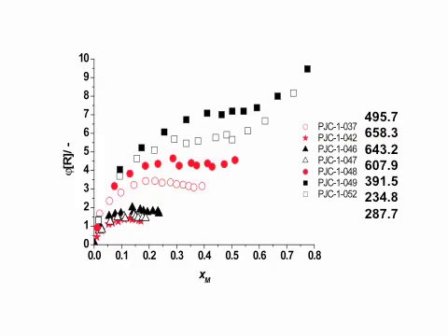But you also see there's a massive retardation effect before you reach that. And we argue that maybe the clay on the interface potentially traps some radicals, and that's why it doesn't react. But that's speculative. And the bit why it goes up here, why it deviates, well, we followed the rate, as you could see on the previous slide, the rate of bulk polymerization was followed as a straight line. So we don't take the Trommsdorff effect into account, and obviously that starts to become important there. So that's the kind of trick you can play with experimental data.